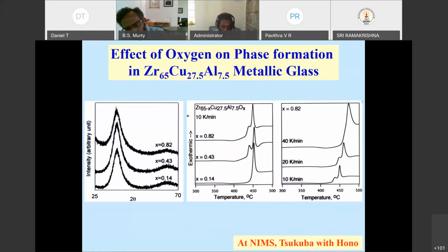And the reason why I went into atom probe those days was we wanted to study how oxygen influences metallic glasses. There were those days people making metallic glasses in different groups, and what is interesting is in some special type of a metallic glass, which is zirconium based metallic glass, depending on the group that is working on that, one group reports that when I take this glass, crystallize it, I get a crystal. Another group says when I crystallize it, I get a quasi crystal. The composition of the alloy is exactly the same.